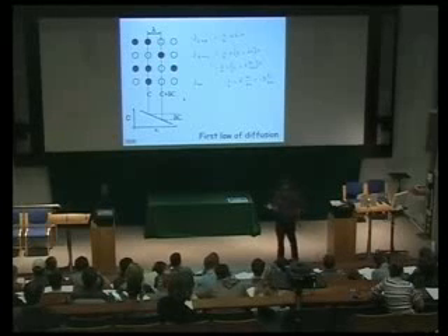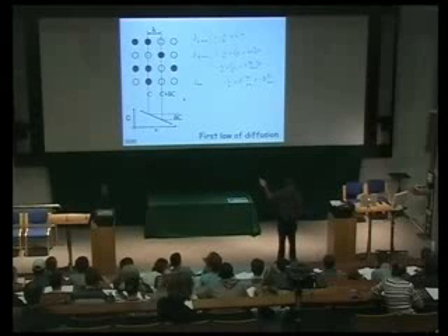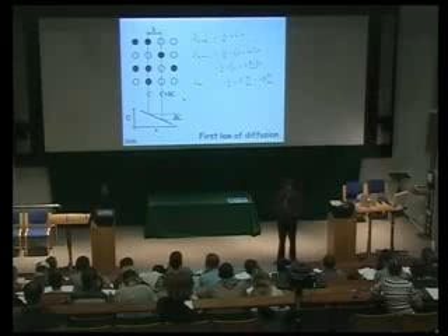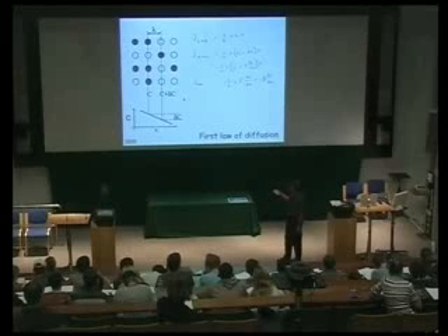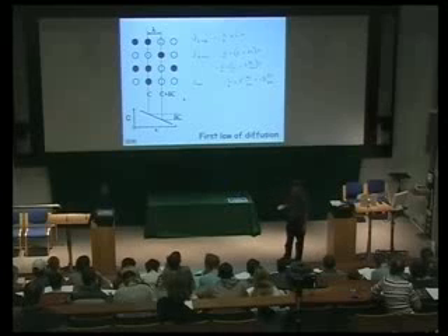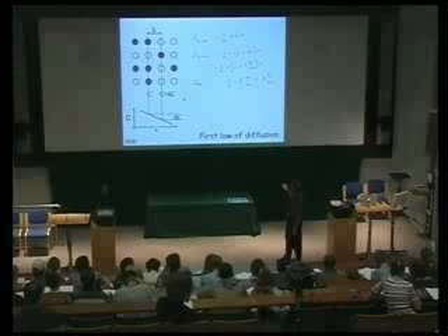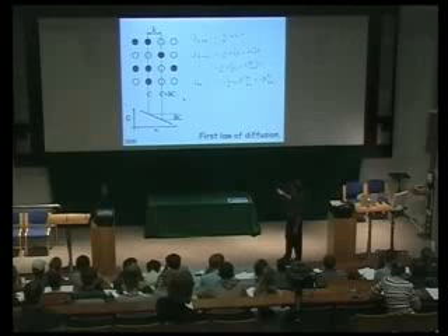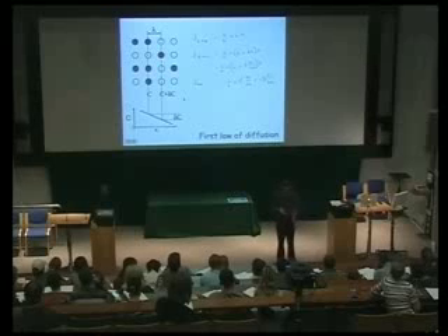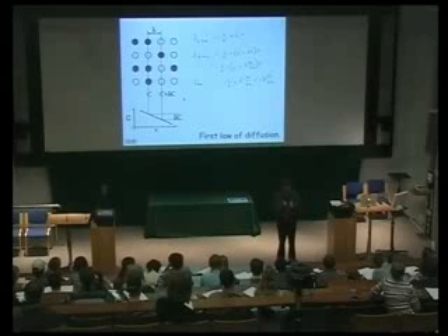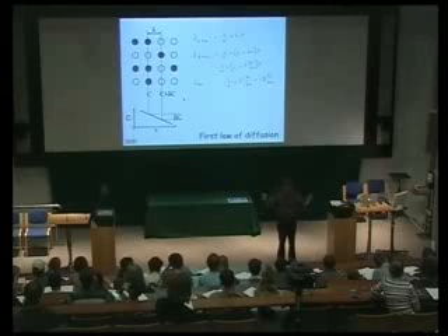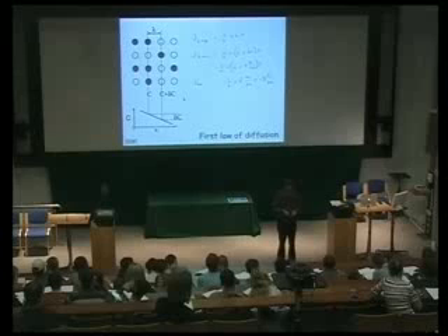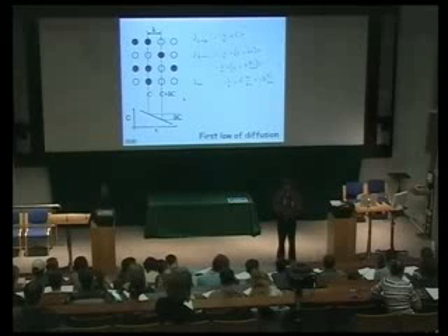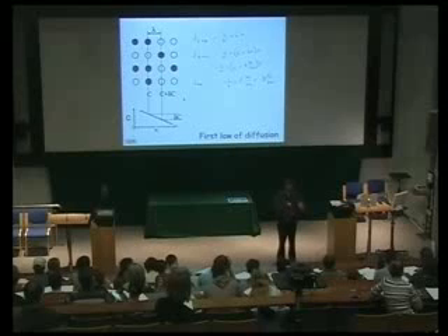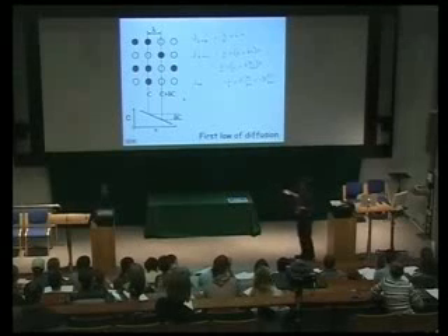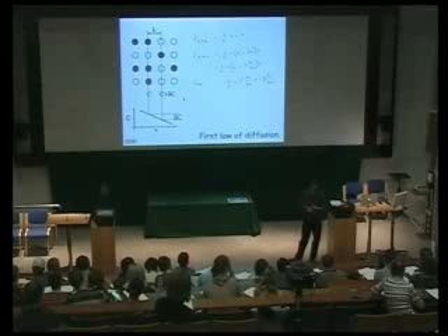So C multiplied by lambda gives me the number of atoms per unit area of solute on that plane. Okay? So this is straightforward. The 1/6 is because the atom can jump in 6 different directions. This is the jump frequency, and this gives me the number of solute atoms on this particular plane, because the thickness of that plane is lambda. Its cross-sectional area is 1, because I've taken a bar which has a cross-sectional area of 1 square meter. So lambda is actually the volume of that plane. If I multiply the volume of that plane by the concentration, I get the number of atoms of solute on that plane. Okay?